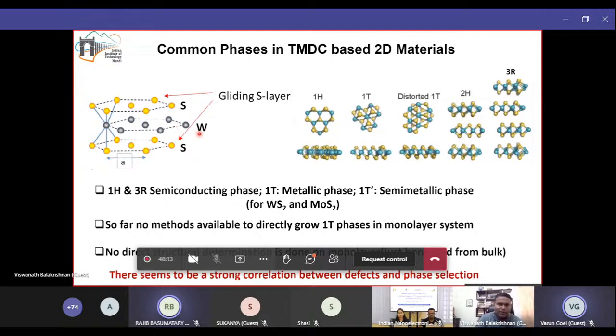Nowadays there was confusion between 2H and 1H. Typically, to have this hexagonal structure, you need 2 unit cells. That is why we call it 2H. But now people are saying we have only one layer. So that is why there is confusion between the bulk crystallography and the monolayer crystallography. Many of the literature has now changed to 1H. So that is the semiconducting, most stable phase you will find for many of the 2D materials.